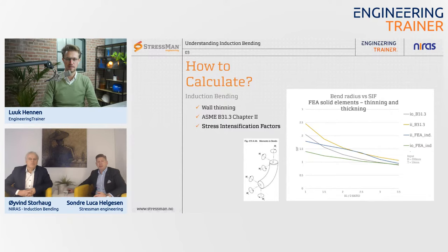where we included the thinning and the thickening effects. We could see that this is still the B31.3 SIF, as well as this one. So this is the in-plane, and this blue line is the in-plane when we include thinning and thickening effects. So you can see that we are always below B31.3, or we are equal to it. The same goes for out-of-plane. This is out-of-plane B31.3. This is out-of-plane FEA. So as we can see, we're still below in every case.